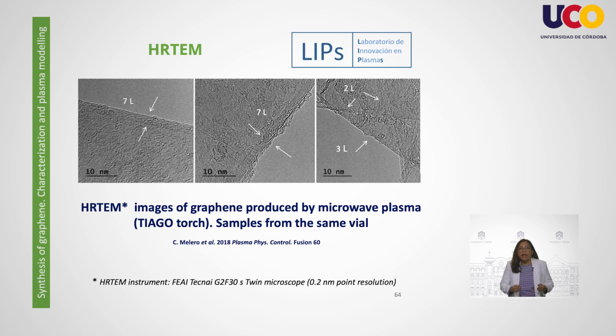Here our HRTEM images show that the produced graphene consists of few layered sheets of 2, 3, and 7 layers without the presence of any other particles such as carbon nanotubes or graphitic particles. This indicates the selectivity of our process in the synthesis of pure graphene and in relation to the formation of other carbon structures.